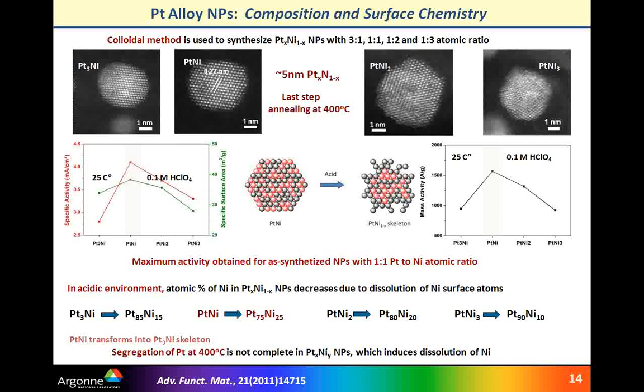So here we increased the platinum-nickel ratio going from 3x1 all the way to 1x3, and certainly a crucial question was what would happen with nickel which is exposed to acidic electrolyte. And we performed a careful study that involved not only electrochemical characterization but also characterization by high resolution TEM, and we were focused on composition change before and after exposure to electrochemical environment. And therefore here you can see the summary, what would be the average or bulk composition in case of different catalysts.